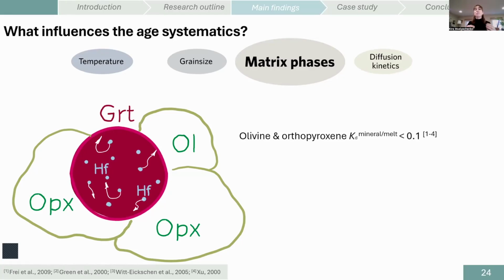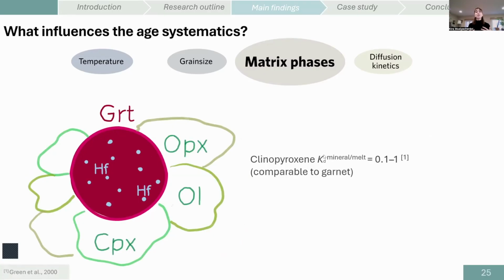We don't have any fluid or melt in the grain boundaries, because remember, very dry, dehydrated mantle. And none of the phases around it wants to take the hafnium in. So the chronometer remains closed, the system remains locked, and the clock keeps going, even above the supposed closure temperature. Everything changes once we introduce the clinopyroxene.